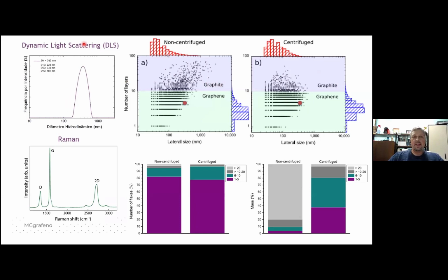Let's go back to the dynamic light scattering and the Raman. This was taken from this sample, the non-centrifuged sample. The dynamic light scattering shows something around 300 nanometers, and the Raman shows you 4 layers. This is the sweetest spot possible that you can get in this chart. It's the best compromise between small number of layers and large size. And this is what these two techniques give to you. And this is what everybody shows.